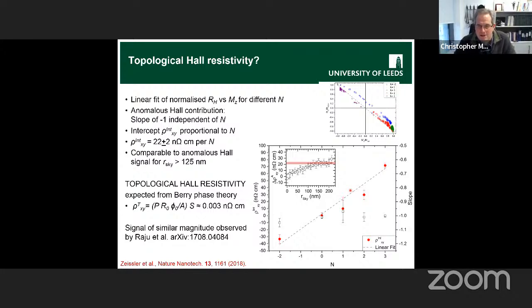Exactly. So here's the number of skyrmions, or the skyrmion winding number: 0, 1, 2, 3, or -2. And then this size-independent bit is the bit that correlates with this, but you can't explain it with this simple formula. If I take phi naught of flux per skyrmion and calculate, you're orders of magnitude away from what we're actually seeing in this experiment. Okay, something to think about.